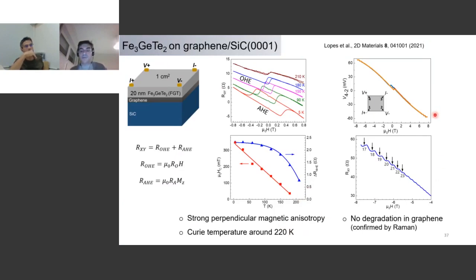And in addition, a very important piece of information here: if we go to very high magnetic fields, we start seeing Shubnikov-de Haas oscillations. This is not coming from FGT, but from the graphene below. And this is very important because it shows that even after growth, the graphene layer below is still functional and is still showing very high mobilities. That's the reason you see Shubnikov-de Haas oscillations, meaning you still have the manifestation of the quantum Hall effect in graphene, which shows that you have a heterostructure. So both 2D materials are still functional, which is very important in the context that you want to have both materials functioning there.